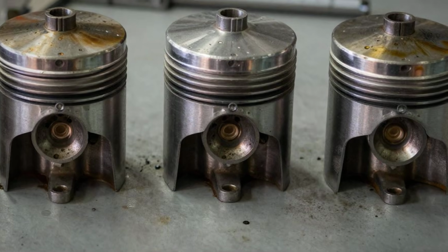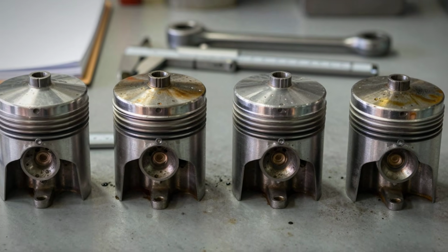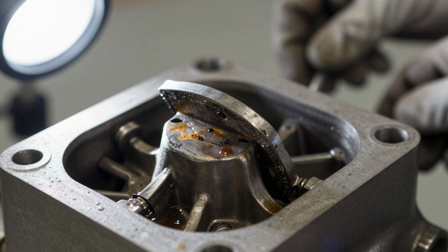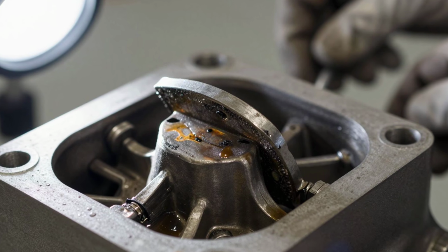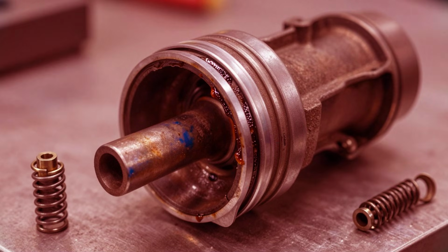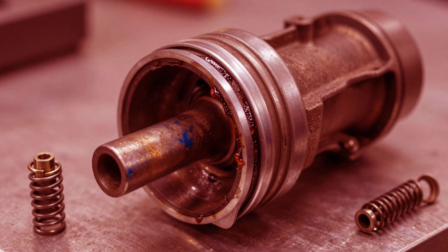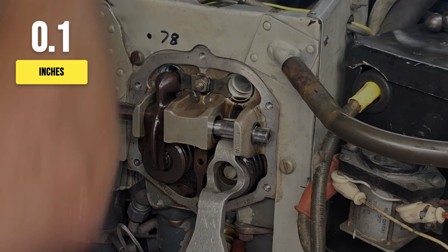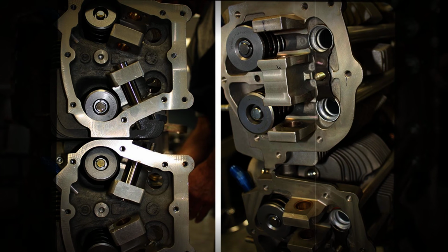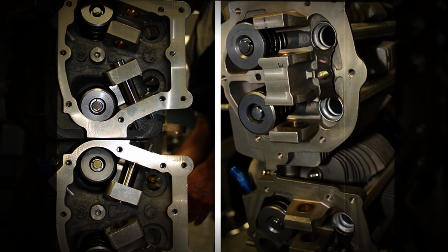Lab logs from the 1950s and recent field reports agree. Pitting starts at 10 microns, but in a matter of months, that can double, triple, until 50-micron craters merge and the contact area collapses. When that happens, the seat loses its shape, the seal goes soft, and hot gases start to leak past every time the piston rises. The recession accelerates, the valve face thins, and the margin that once measured a healthy 60 thousandths is hammered down to 20, then 10, then nothing. Mechanics call it recession, but it is really the slow march toward terminal failure.